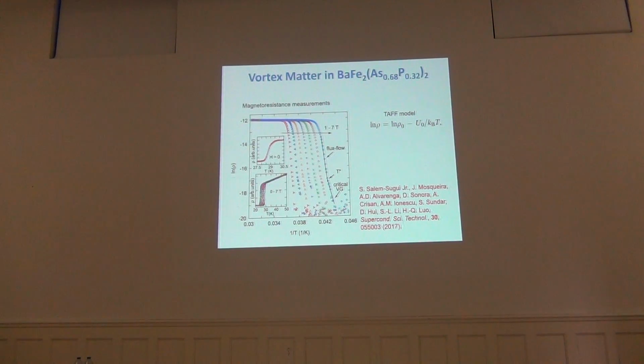Now, magnetoresistance measurements were performed in a quite wide range of resistivity. The thermally activated flux flow model was used, and we got these results here, where we have a flux flow, a critical vortex glass and a crossover temperature, and all these things have been published in this paper last year.